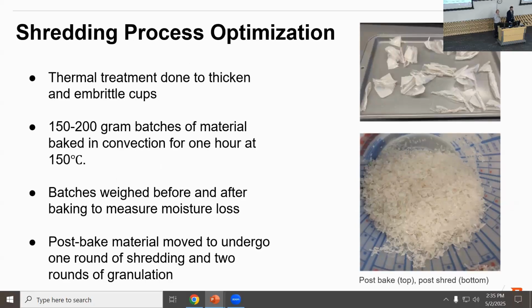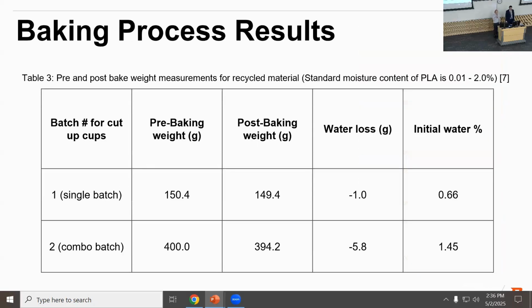So we applied this to our shredding and processing optimization by thermally treating our cups. After sectioning them into smaller pieces, we weighed out about 150 to 200 gram batches onto metal trays and baked them for 1 hour at 150 Celsius. They're weighed before and after so we can see how much water we lost. And so this is the result of that. We found that the highest amount of water that any of our samples had was 1.45%, initially, which is well within the industry standards for PLA, which goes between 0.01 all the way up to 2%.